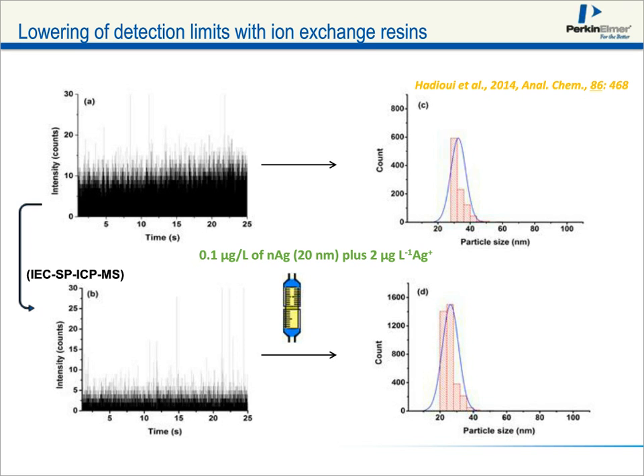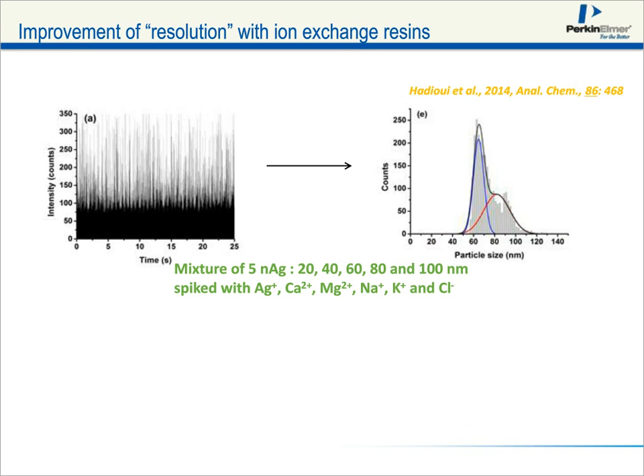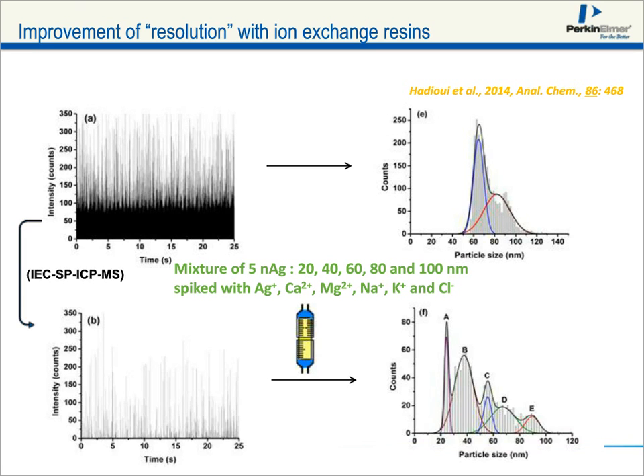This one's even a little nicer. We've got a mixture of 5 different nanoparticles, and you see by single particle ICP-MS, we can pull out 2 peaks from that when we're in the presence of all these other dissolved ions. But when you run this first through an ion exchange resin, we again remove the dissolved, and you can really pull out all 5 of your nanomaterials.